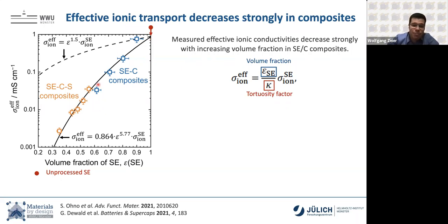In any case, we can measure this effective ionic conductivity as a function of the volume fraction of our electrolyte. First, we do that with just solid electrolyte carbon composites, and then with solid electrolyte carbon sulfur composites. But this is the composition, or the volume fraction of solid electrolyte, that we have in a composite cathode. This is the ionic conductivity up here that we wanted, or let's say we're at 1 millisiemens. This is where we started with.